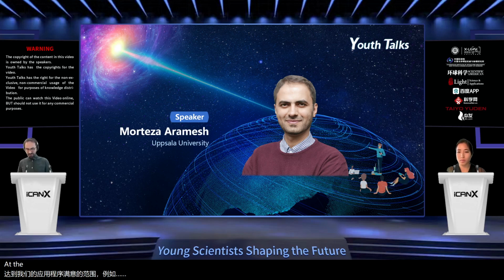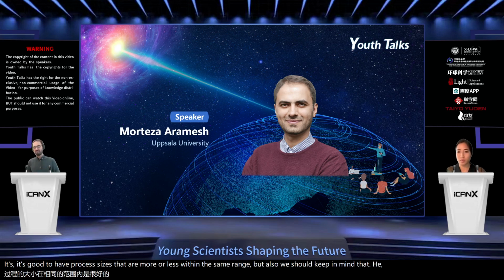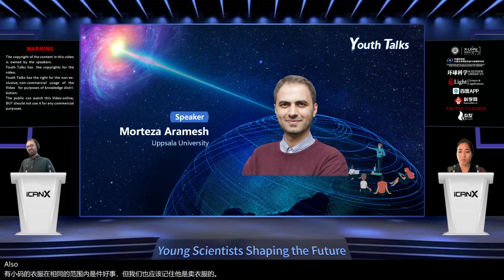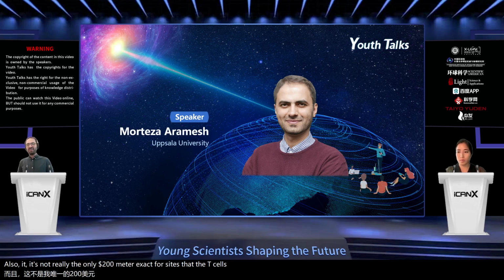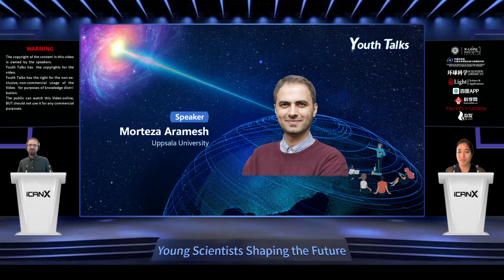At the same time, there is a lot of room for improvement, and it's good to have pore sizes that are more or less within the same range, but we should also keep in mind that it is not only the exact 200 nanometer pore size that the T cells would react to. There is also a range of pore sizes around 200 nanometers that the T cells can get activated by entering the nanopores. So it gives us a little bit of room to work with a wider distribution of the pores.